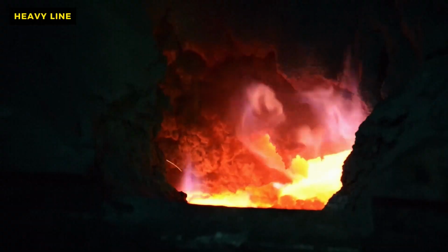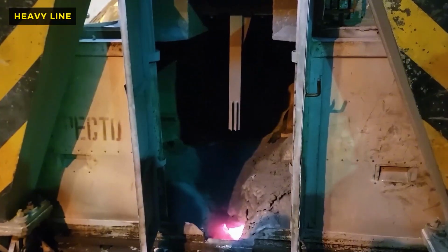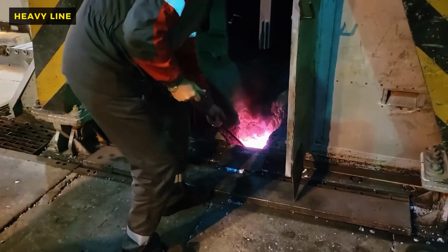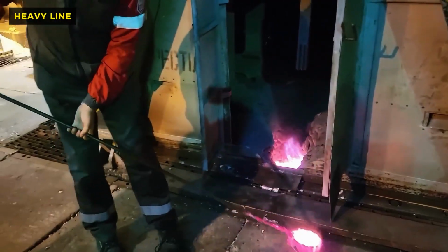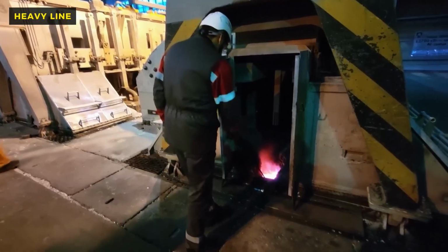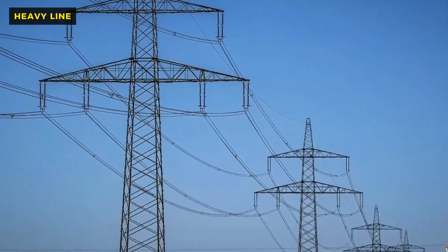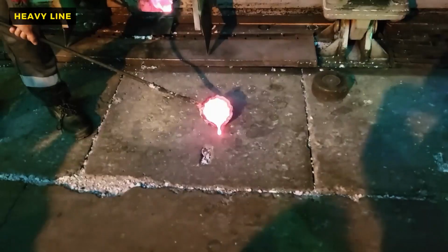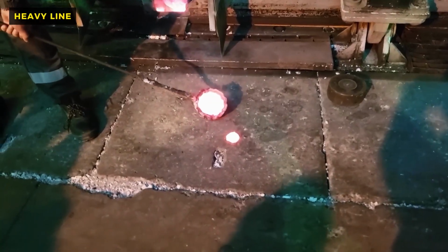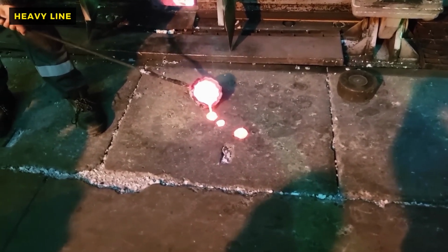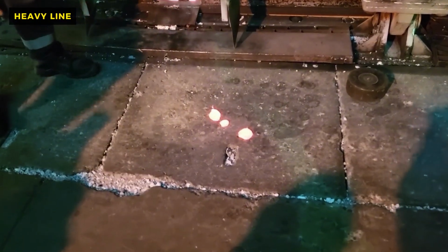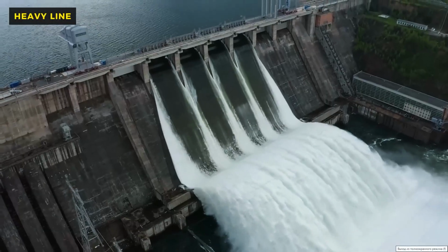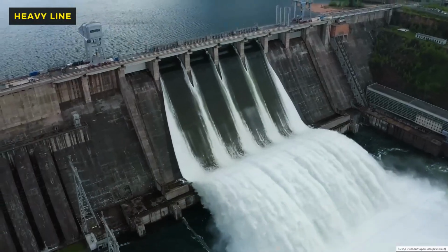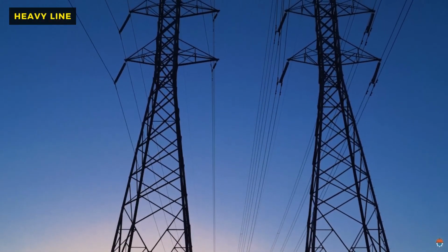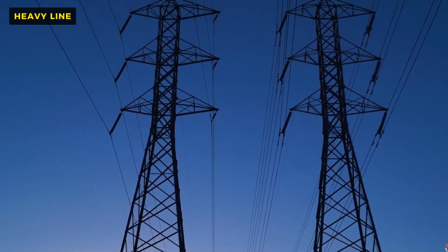The liquid aluminum and electrolyte actually swirl and wave under the influence of the magnetic forces, a hydrodynamic instability that engineers must carefully model and counteract. If the metal surface waves too much, it can touch the anode, causing a short circuit. To prevent this, the bus bars are routed in complex, computer-designed geometries to cancel out magnetic interference, effectively using the magnetic fields to pin the metal down and keep it flat. It is invisible sculpting, using the forces of electromagnetism to flatten a liquid mirror of molten aluminum hidden beneath a crust of salt.